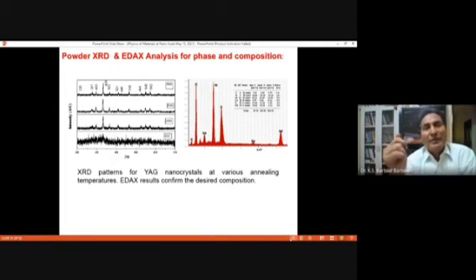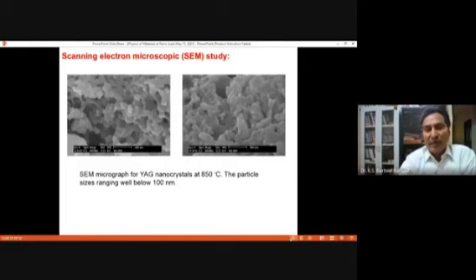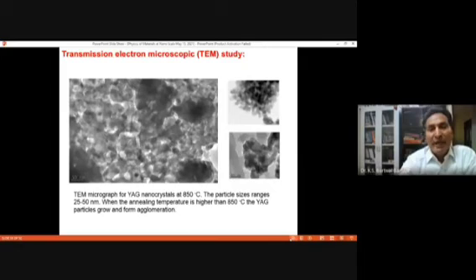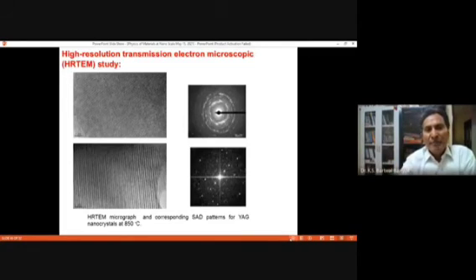And again, we go for XRD, EDX and other techniques for making sure that it is a single phase, a single crystal, and in the whole area it is a single phase material. Then scanning electron microscopy doing the same thing. Then transmission electron microscopy again for knowing the structure as well as the size of the particles, which is supposed to be 25 to 50 nanometer, well enough to make any device out of it. When we make devices out of these nanomaterials, they work like a single crystal of YAG. High resolution is for getting the atomic size and atomic unit cell of that material.